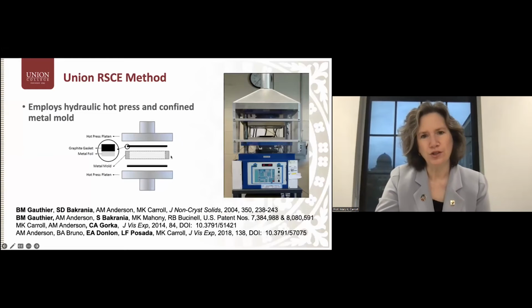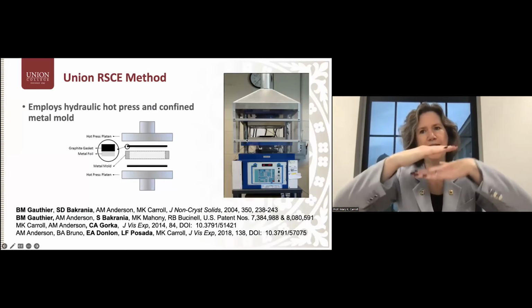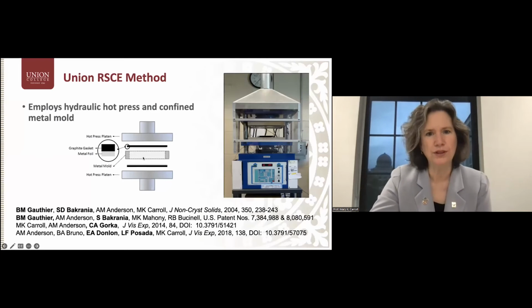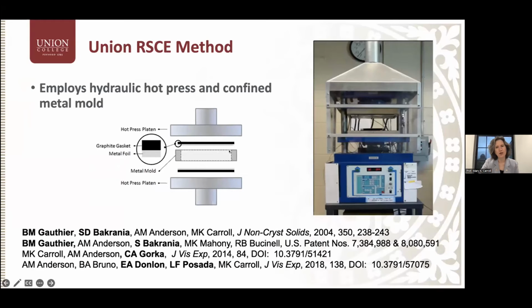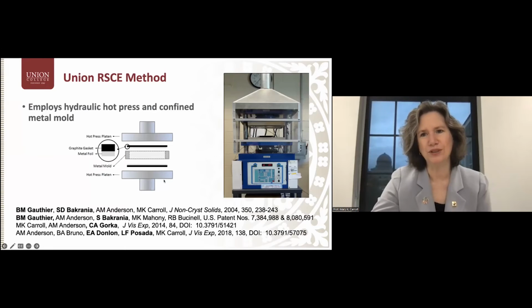And so what we do is we form the gel within a confined space in a metal mold, and we put the metal mold into a hot press and then close the platens of the hot press around the mold using suitable gasket material, so typically graphite and a metal foil. So the precursors are put in, we close it in place, and then we use the hot press to drive up the temperature of the platens, which drives up the temperature in the mold. And in the next slide, I'll talk you through the process in more detail.